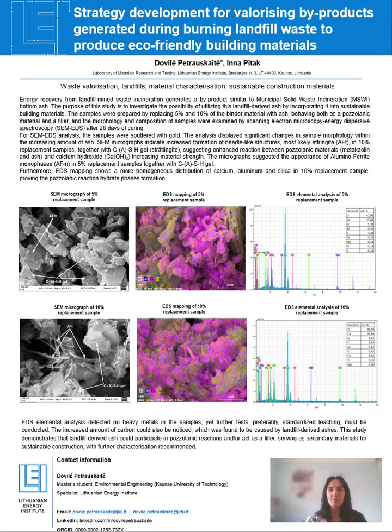So the transition from AFm-type plates to AFt-type needles reflects the evolution of hydration products as the ash content increases. And EDS mapping also supports these observations. In the 10% sample, the distribution of calcium, aluminum, and silicon is more homogeneous, indicating better mixing and more complete hydrate formation. And the spectra show strong calcium and silicon peaks, moderate aluminum, and also traces of iron, which is consistent with pozzolanic reaction products.